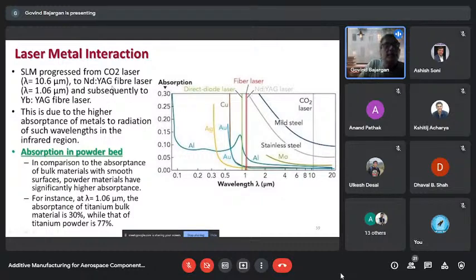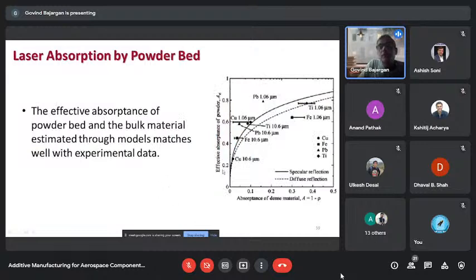Then it was changed to neodymium YAG, and then ytterbium YAG fiber laser. When it became neodymium or ytterbium fiber laser, the absorption on aluminum and others increased, but still for copper it is very less. But all these data are for solid pieces. So we want to know how the powder bed behaves. What was found is that the powder bed gives more surface area, so absorption is far better than dense material. Like copper with the fiber laser, with the 1.06 micron wavelength, its absorption is around 60% of the laser energy, whereas dense material absorbs only 10% of it.